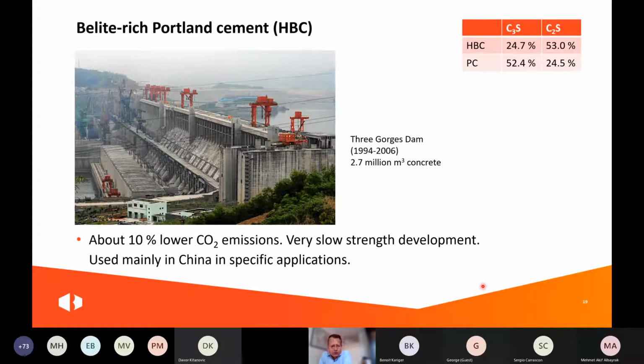This is the first alternative, belite-rich Portland cement. This is a little bit back to the hydraulic lime I mentioned earlier, although not using limestone calcium hydroxide, but mainly using belite. Here you see it. The high belite cement has a relatively large amount of this belite and a relatively low amount of alite, the quickly reacting component of regular Portland cement clinker.